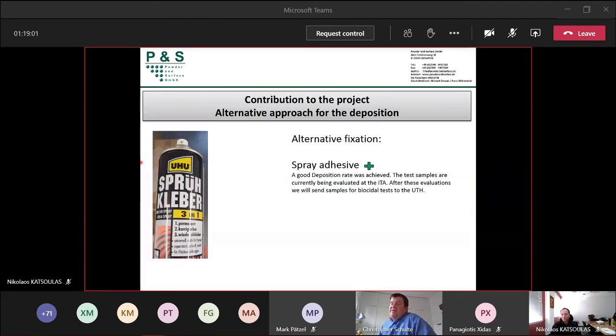So the idea before, to use an adhesive, a glue, was very important. And if we find out that the nanoporous structure is not killed by this glue, then we are convinced we could offer an interesting alternative to the plasma jet to melt in and fix the particles on the surface. But they are not melted in then. They are only fixed with the glue on the substrate, on the fabric. And the question is now, is it then effective against bugs or not?